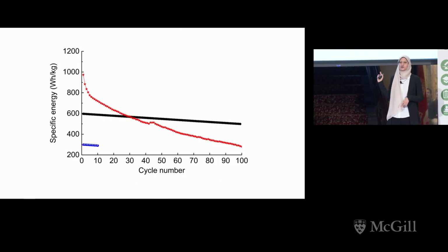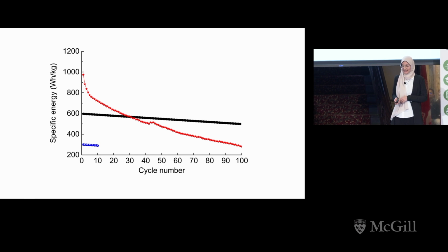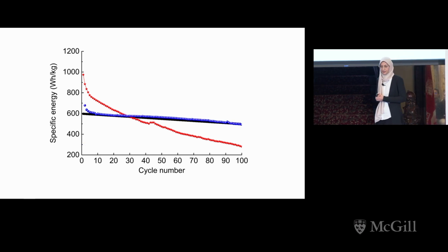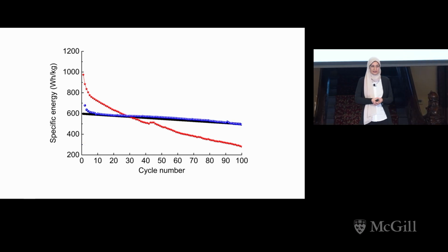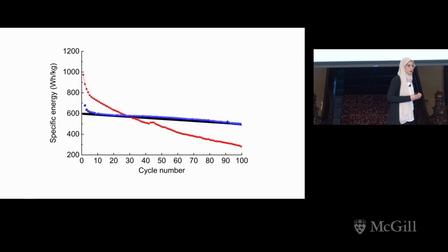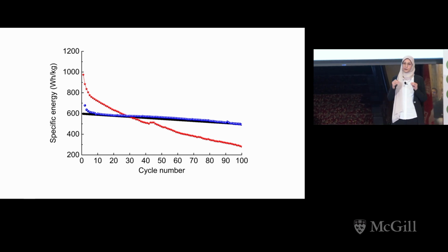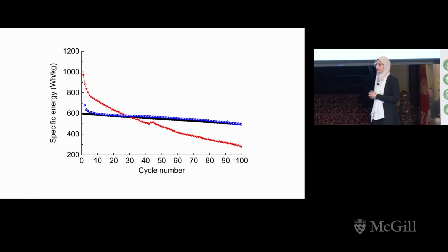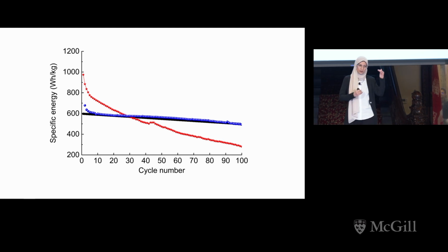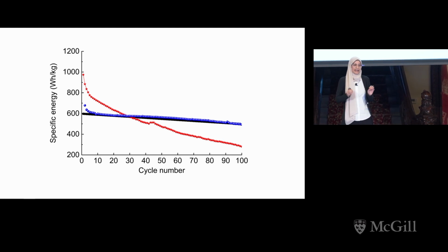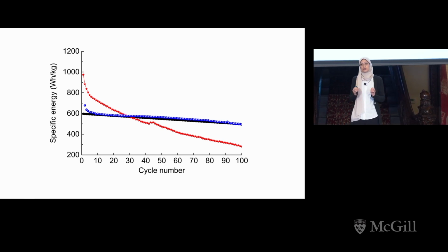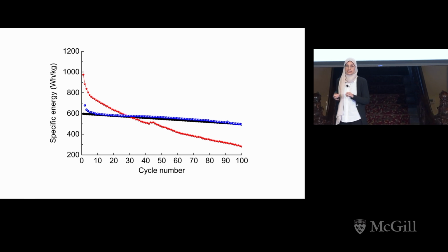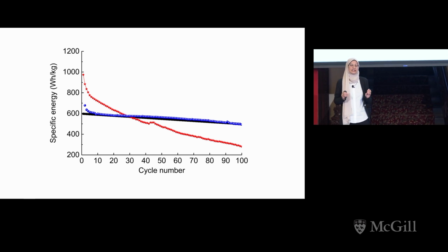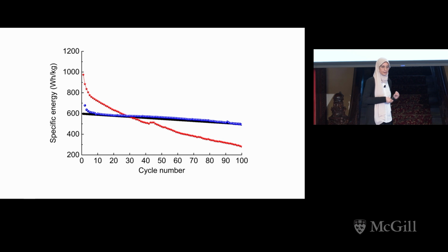Oh, it's not this one—this was the terrible one. This is the real performance. As you can see with the blue line, with our synthesis method, we were able to obtain a stable 600 watt-hour per kilogram. It's still not 1,000 watt-hour per kilogram, but at least our material is comparable to the commercialized material, or the layered material that has been extensively studied for decades.